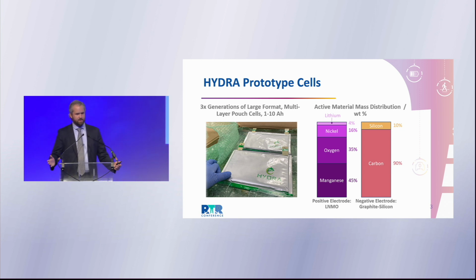But I mentioned we're developing materials or researching materials. What are these materials? Well, we can see in the figure here, on the positive electrode side, we're using a material that consists of lithium, nickel, manganese, and oxygen, LNMO. Which is a high voltage material, obviously free of cobalt, and relies mostly on relatively abundant materials like manganese and oxygen.